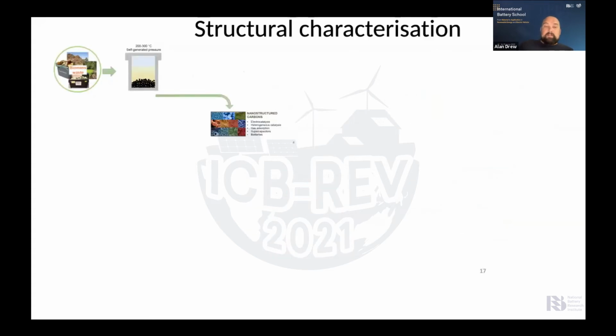So let's go back to this structural characterization. How does this work? So we take biomass, we put it into a pressure vessel, we cook it in a hydrothermal pressure vessel for a few hours at 200 degrees C, and then we take it out and we anneal it.